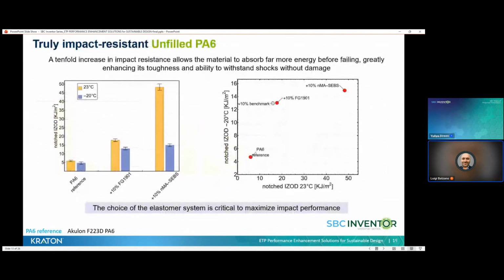On the other hand, when looking at the impact resistance performance, due to the different deformation mechanisms that are relevant at this loading condition, the situation is completely different. This slide shows impact resistance measured in terms of notched Izod, and it is clear that the new modifier exceeds FG1901, and it is not shown here, but it exceeds most other commercially available modifiers.